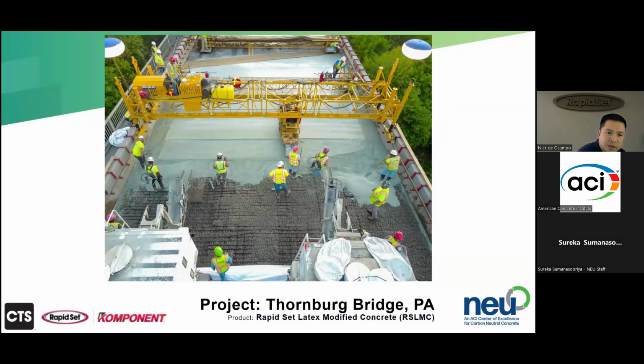This is a technology I didn't talk about yet - the Thornburg Bridge in PA, using Rapid Set Latex Modified Concrete, RSLMC. Latex is added to the bulk concrete production to prevent the intrusion of chlorides, specifically from de-icing salts, from penetrating into the concrete and reaching the rebar below. If those chlorides reach the rebar, it causes rusting and corrosion, reducing service life and possibly damaging the bridge. So the addition of latex to the mix serves as a corrosion inhibitor.